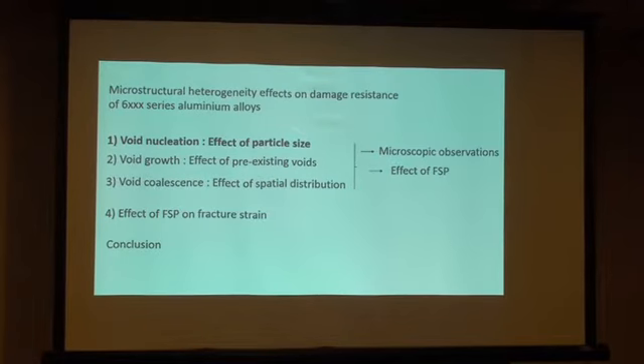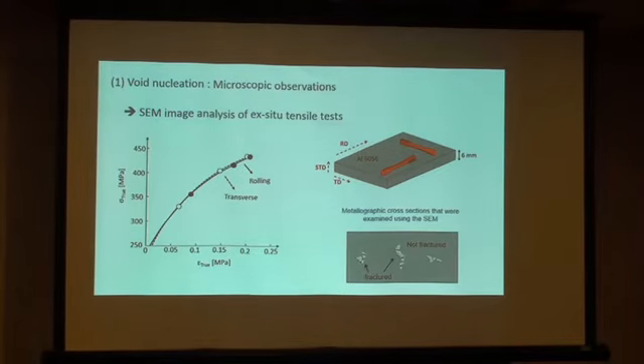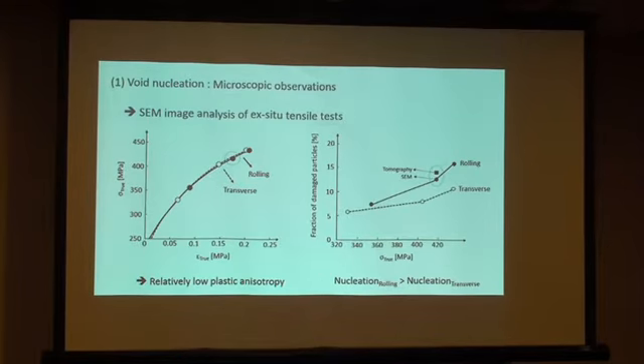I will first talk about the effect of particle size on void nucleation, then pre-existing voids on void growth, and the effect of spatial distribution on the void coalescence process. So what we did first is that we took samples in the rolling direction and in the transverse direction. We stopped them at different levels of stress, and we did some quite classical metallographic observation. So we polished the sample until mid-thickness, and we could see if the particles were broken or not. By doing this, you can see that, as I was telling you earlier, the plastic anisotropy is not big between the two directions.